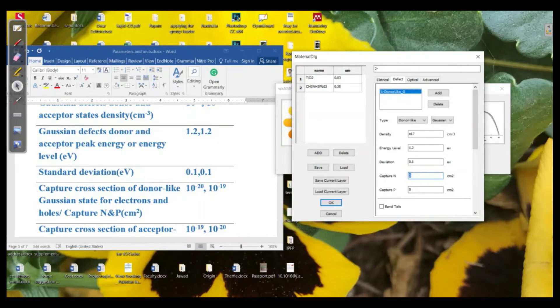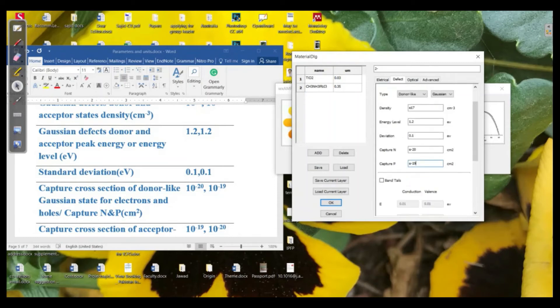The capture cross-section for electrons in the donor-like Gaussian state is about 10⁻²⁰, and for holes it is 10⁻¹⁹. For the acceptor-like state we just need to switch these numbers: it will be 10⁻¹⁹ for electrons and 10⁻²⁰ for holes.